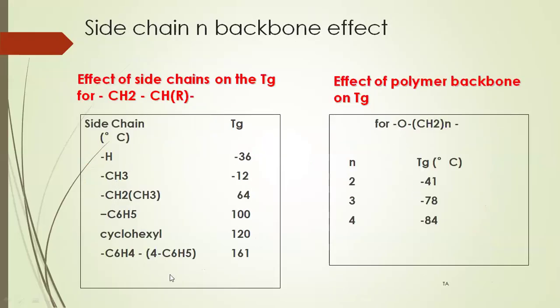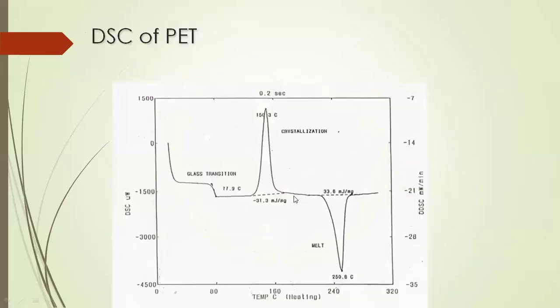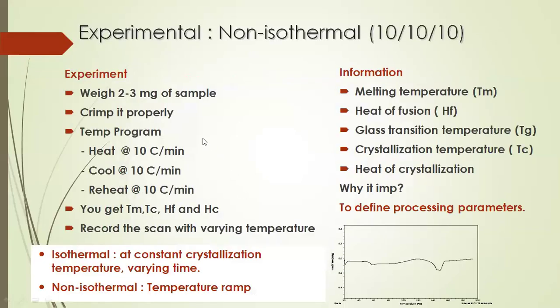Also the side chains: if you increase the bulkiness of the side chain, your glass transition temperature increases. Polymer backbone also: if you add flexible chains in the polymer backbone, your TG decreases. This is just to recall how DSC looks. Two types of experiment you can do using DSC. One is non-isothermal experiment, which is very common, and second is isothermal experiment. Non-isothermal, as the name indicates, is a temperature ramp, and isothermal is at constant crystallization temperature with varying time.